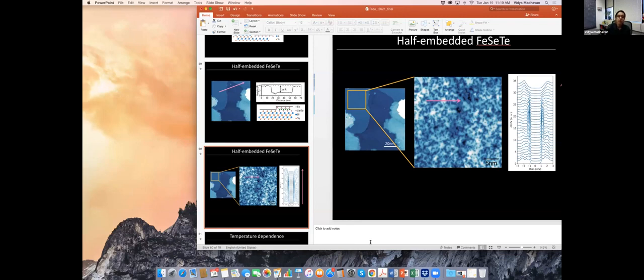So you're not growing it by evaporating Fe, Se, and Te. Instead, we're depositing only iron on top of bismuth telluride, and then annealing in a selenium-rich atmosphere, and that's it. That's what gives you this. So the proof of the pudding is that you do that, and you don't end up with any excess iron. It's really nice. Okay, thank you very much.